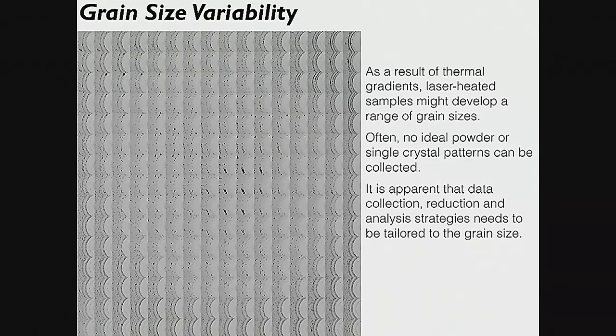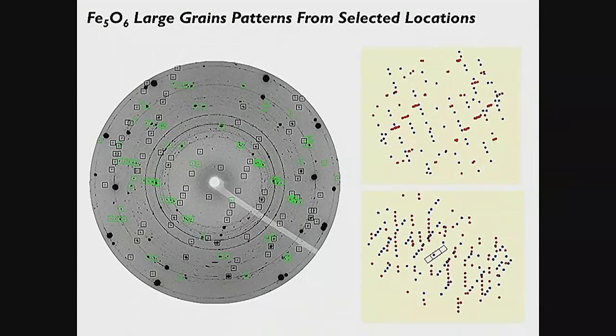These are stationary images, and you can see how you have a rim of fine grain sample. Still, none of this is technically a good powder, a good statistics powder. You go to the mesoscale, and you have single crystals in the middle. So what I do is try and collect the best data in each spot. For some samples, I might be able to have multi-grain single crystalline powder from the same 20, 30 micron size sample.